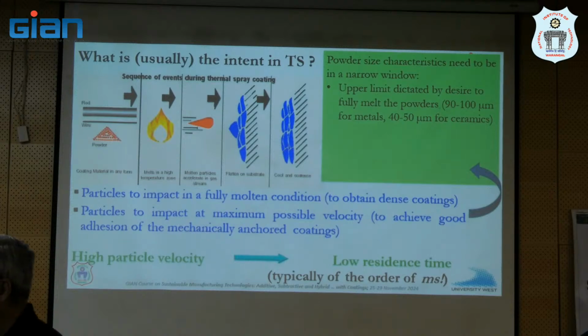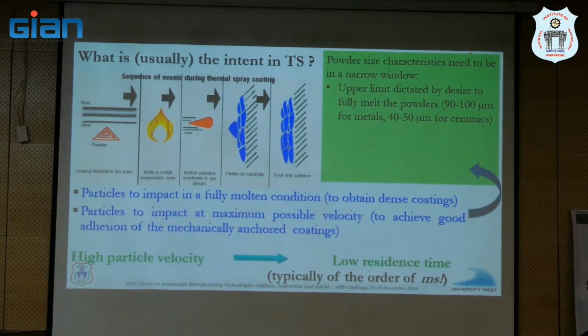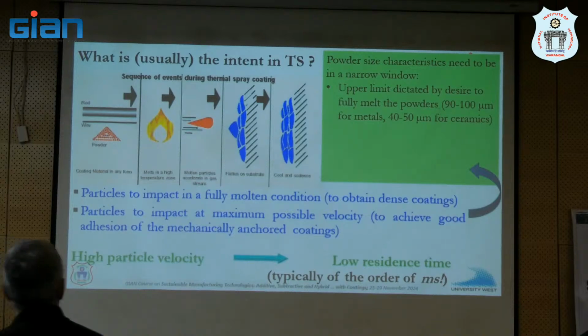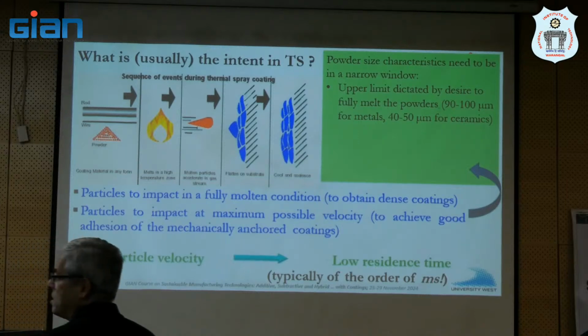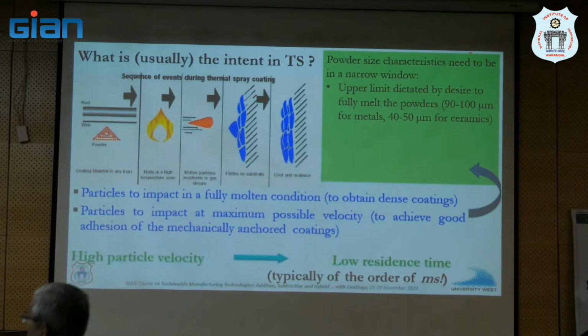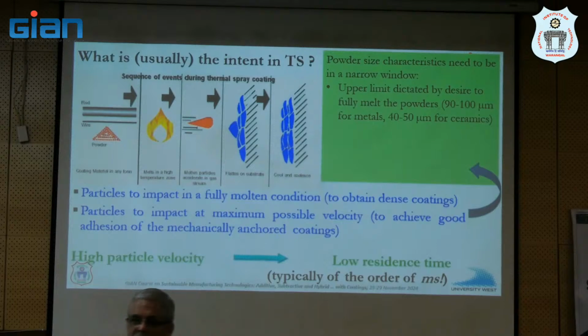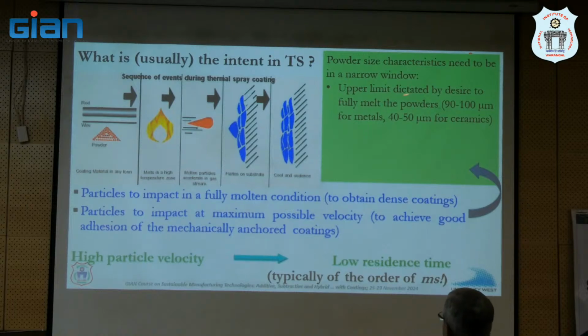If they are ceramic particles which are high melting, then they have to be finer. You have to be 45 microns or less. Otherwise, they don't melt in that short residence time that is available. If they are metallic particles which have slightly lower melting point, you can go a little bit higher. Maybe you will see particles which are 90 to 100 microns. But more than that, you can't spray. Yeah, I mean, you can't spray in the sense you will not fully melt, correct? So that imposes the upper particle size limit.